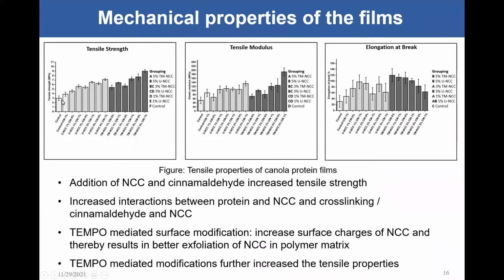We did add cinnamaldehyde because we wanted to check the possibility of making antimicrobial film at a later stage. But when we add the essential oils, if the mechanical properties are decreasing, then that's a disadvantage. So we didn't focus on the antimicrobial properties, but we added the cinnamaldehyde as an additive just to see whether there is any impact on the mechanical properties. With the addition of the cinnamaldehyde, there is an increase in the tensile strength, almost up to 4 megapascal. With the unmodified nanocellulose, you can increase the mechanical properties from 3 megapascal all the way up to like 6 megapascal when you add nanocellulose at 3% weight by weight of protein. The important part is when you add, let's say, 5% modified nanocellulose, your tensile strength goes all the way up to like 7 megapascal. If you add 5% nanocellulose with 1% cinnamaldehyde, you can increase that tensile strength almost up to 9 megapascal.